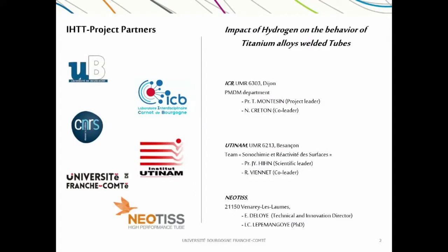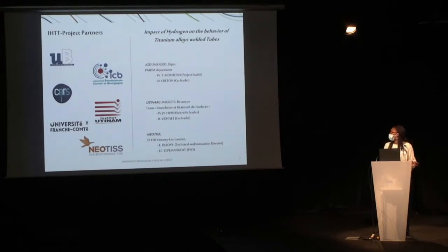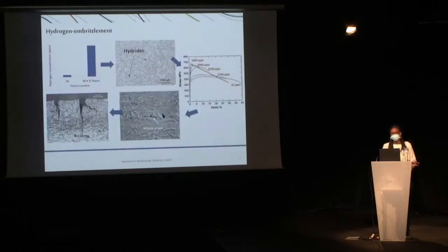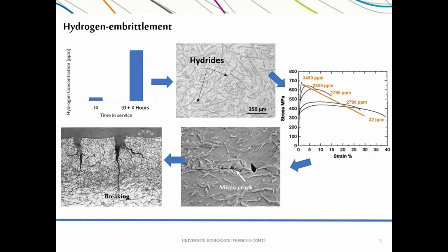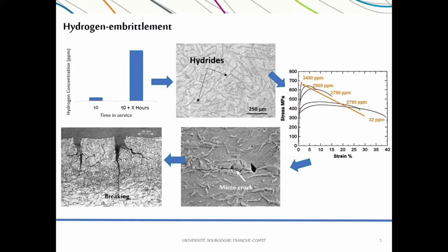Why is it important to avoid the phenomenon of embrittlement by hydrogen? Titanium alloys have a great affinity with hydrogen. When the quantity of hydrogen increases in the material and the solubility limit is reached, we see a precipitation of hydride in the material. This hydride modifies the mechanical properties of the material. The more hydride in the material, the more brittle the material is. Then, microcracks and breaking can appear in the material during the service life.